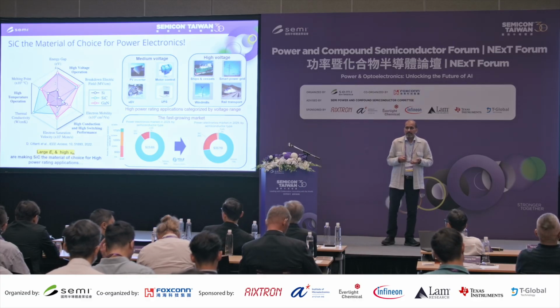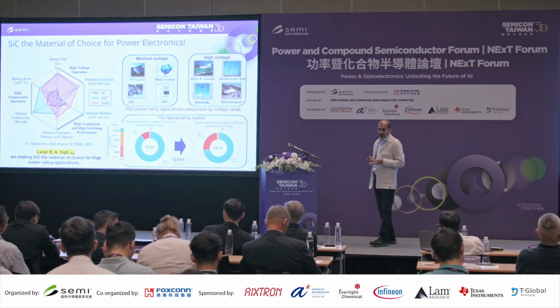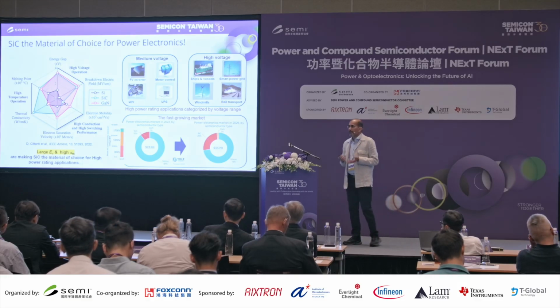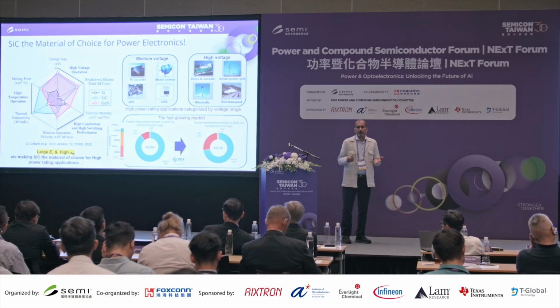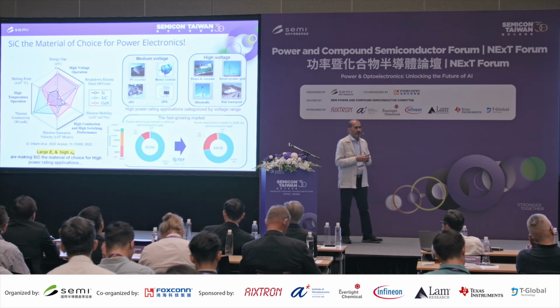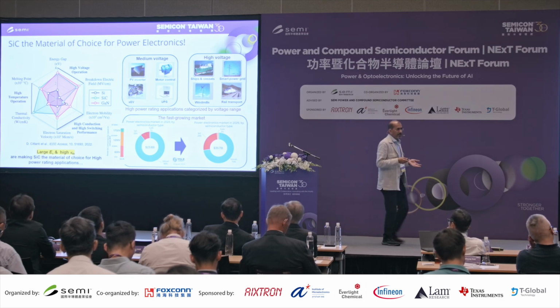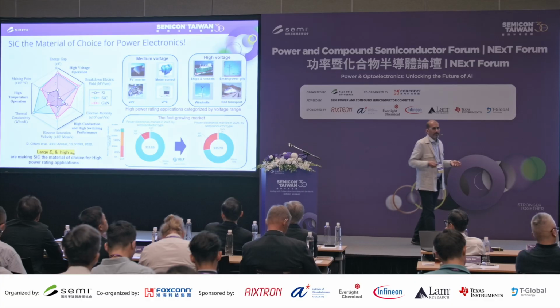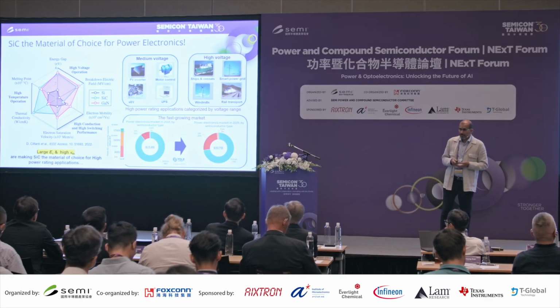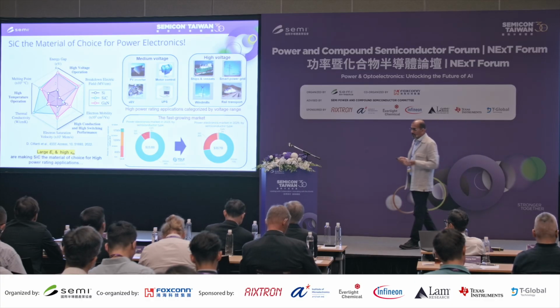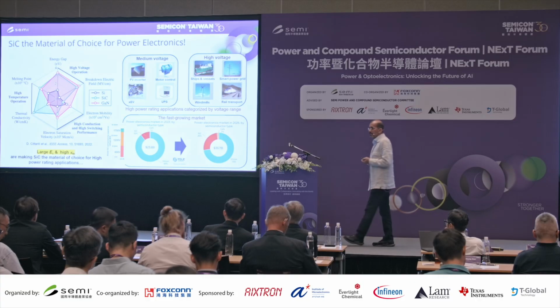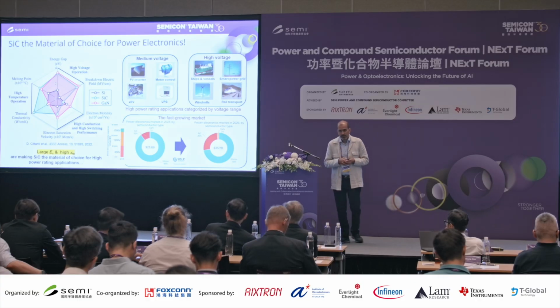The material is having very, very high thermal conductivity, which is allowing this material to shrink the device. Means your power density is very high, heat can be extracted. If it is silicon or gallium nitride or other materials, it's very hard to extract the heat, but in case of silicon carbide, you can easily extract the heat.